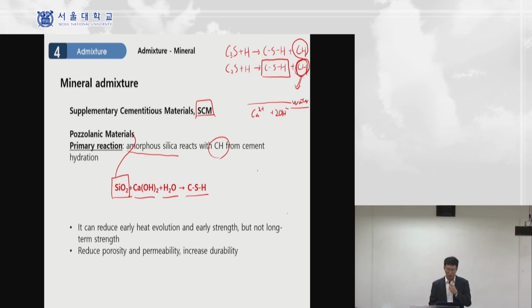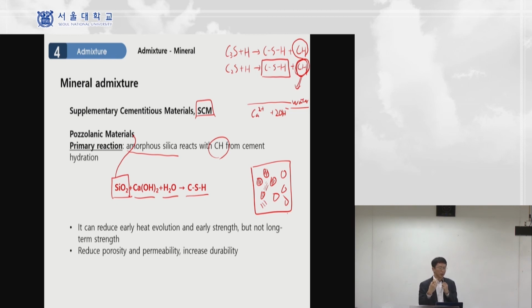So we learned that in the pore structure, we actually have water filling the pores, right? This is concrete, it has pores, right? And it has micro scale, millimeter scale, or sub-micro scale, different scales of pores in the concrete. But for small pores, less than 100 micrometers, for example, these pores are actually filled with water. And the calcium silicate hydrate also contains water between the interlayers, right? So although we cannot see the water directly, we can explain a lot of things about the concrete by knowing that the concrete contains water inside.